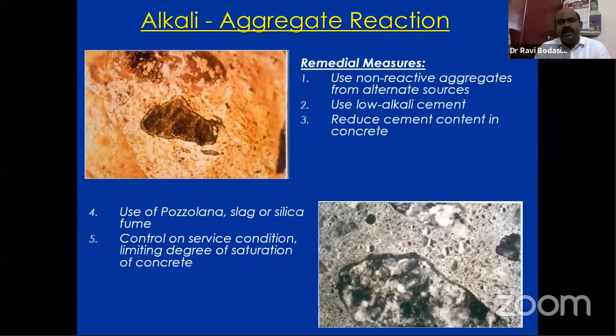So what are the remedial measures for alkali aggregate reaction? Use non-reactive aggregates from alternative sources. If the aggregates are more prone to this silica, then we have to go for another source of aggregates or raw materials, or use low alkali cement, reduce cement content in the concrete, use pozzolana, slag or silica fume, and control service conditions, limiting the degree of saturation of the concrete.